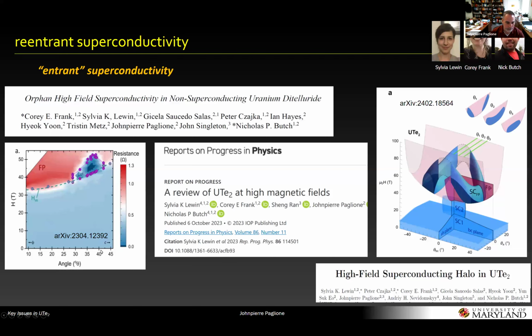So this is quite interesting because it says that even if you don't have a superconducting state at zero field, you can induce it by cranking the field up to 40 Tesla. And again, I think this needs to be studied as a systematic function of triple R and so on, sample quality. But at least in a sample that has no superconducting state, it's still there. Right, so there are some quantitative questions, for instance, this region does seem to shrink a little bit, so is it just a matter of amplitudes? Or is there something really special about this phase here? It's more immune to pair breaking than the zero field phase. Quite unusual, nonetheless.